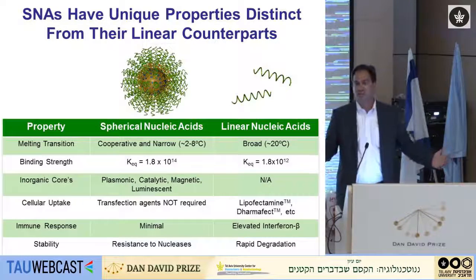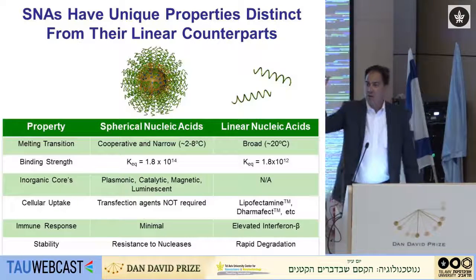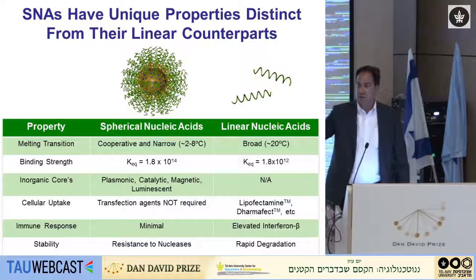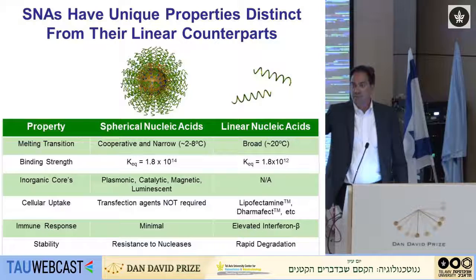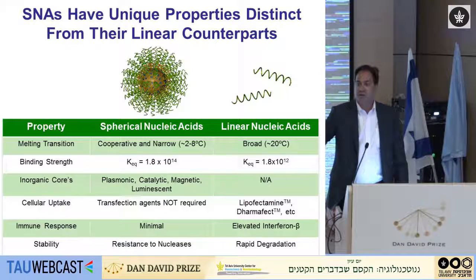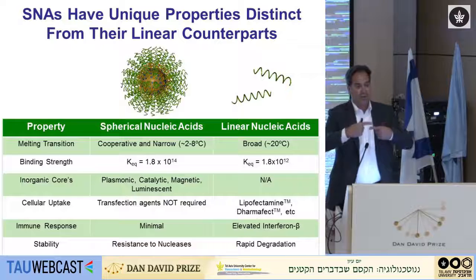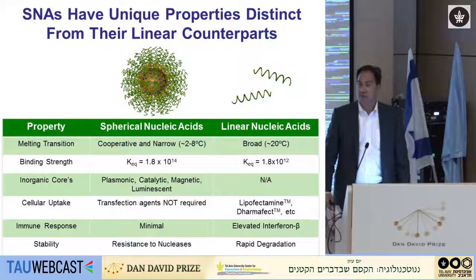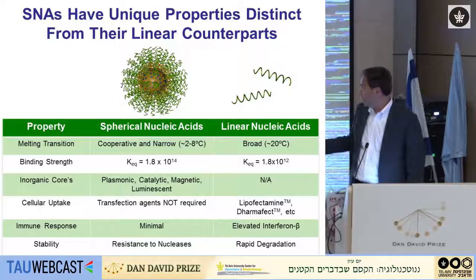Why is it? That's not just phenomenological. It turns out when you tack oligonucleotides down into this spherical architecture on a surface and pre-orient them, you wipe out a lot of the entropic penalty associated with hybridization or forming the duplex. And for that reason, spherical nucleic acids on a sequence-for-sequence basis will always bind complementary nucleic acids more tightly. That's a powerful concept. What that means is you can begin to create probes, for example, that soak up lower concentrations of target than the same sequence with, for example, a molecular fluorophore probe with a single-stranded type of architecture.